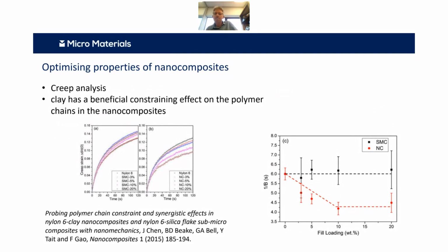So what's going on? Why is the nano better, apart from saying so quantitatively? Well, it turns out you can use the advantage of having had that long hold period in the experiment. Rather than this creep being a headache that affects the accuracy of the unloading measurements unless you account for it, we say it's actually a useful thing in itself to look at and study. So here we're able to apply some simple analysis we developed to look at time constants.